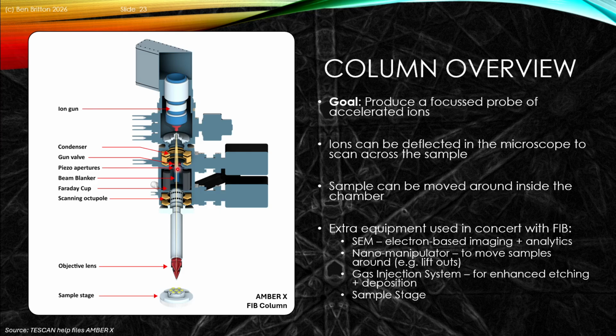Once we've got the beam in the microscope, we can then choose whether we want to blank and send the beam off somewhere else, or we can put it on our sample when we need. And so then this beam can, when it's behaving itself and we like it, be sent down the microscope, and we can go through effectively a scanning octupole that enables us to deflect the beam across the surface of our sample. And then we have basically down to the objective lens and the end of the pole piece, and then it inserts itself into the electron microscope to enable us to target this at our samples themselves.